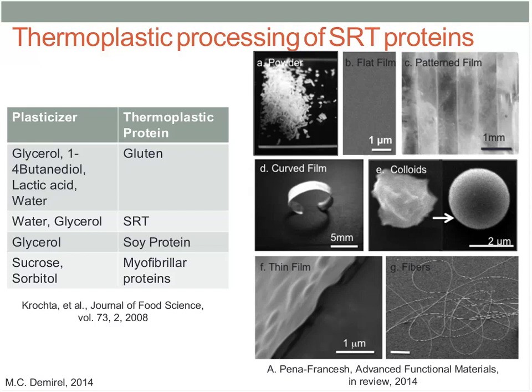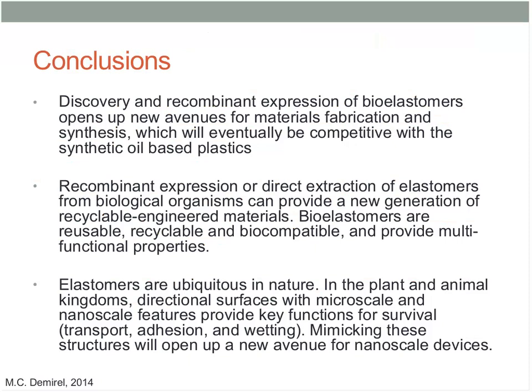The stiffness values of 1 gigapascal in dry and underwater conditions at room temperature are measured. The modulus of the elastomer drops to 10 megapascal above the glass transition, which is similar to the modulus of elastin. Fabrication and synthesizing materials resilient to environmental factors have been achieved by studying functional transition of biomimetic systems both computationally and experimentally.